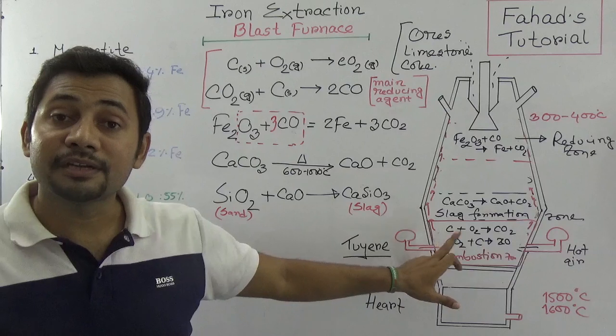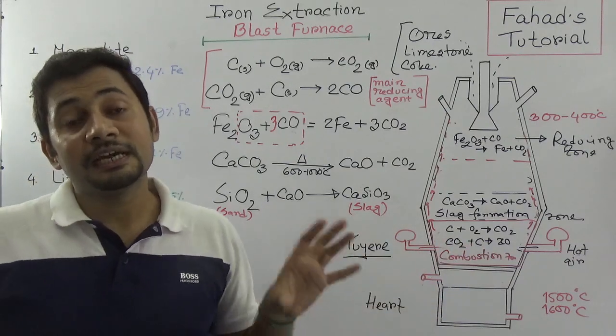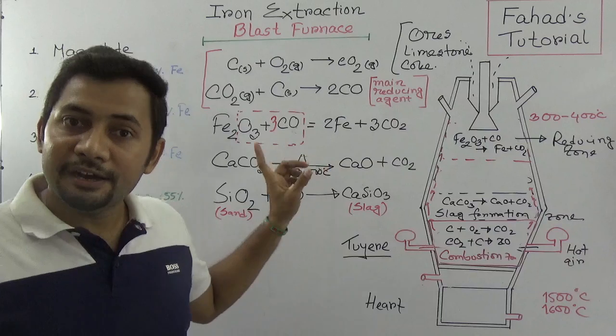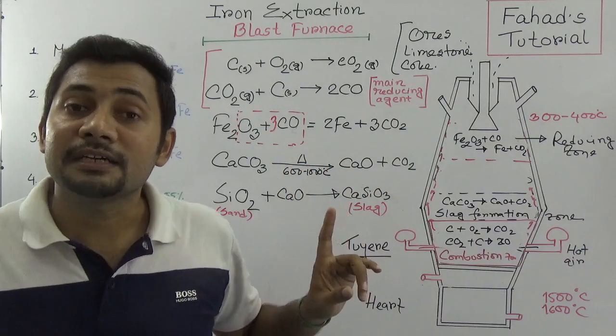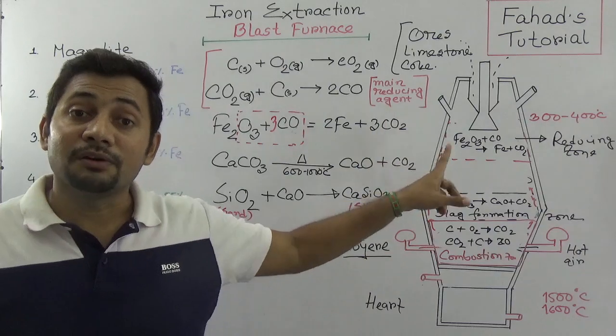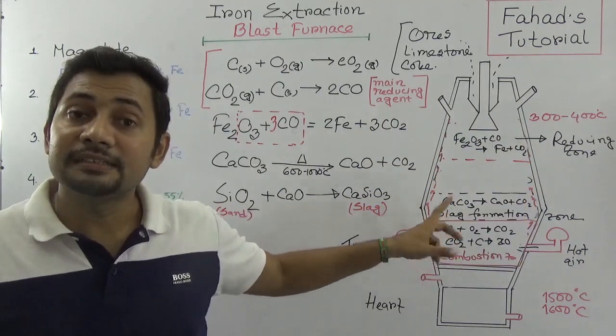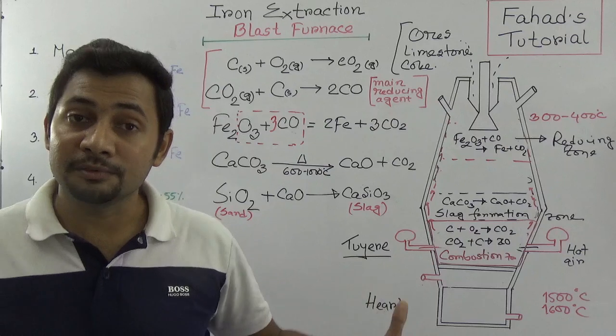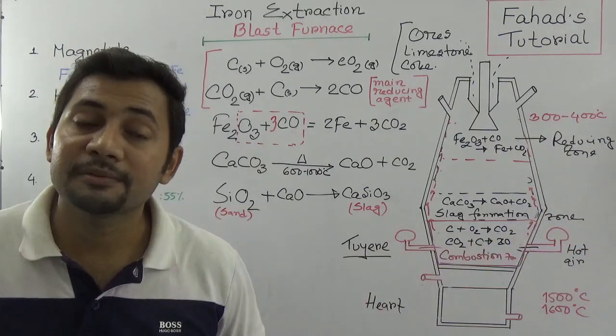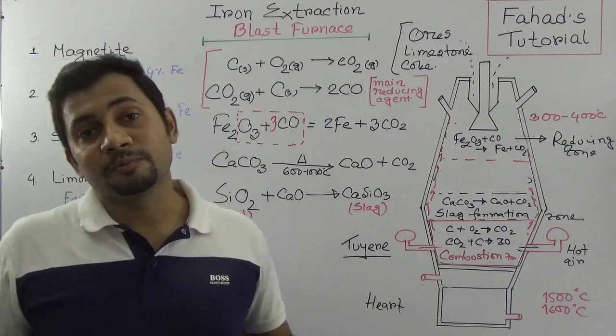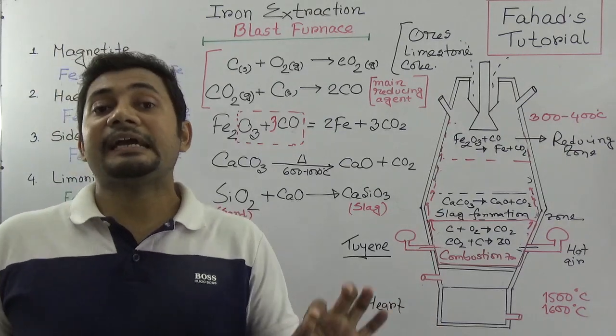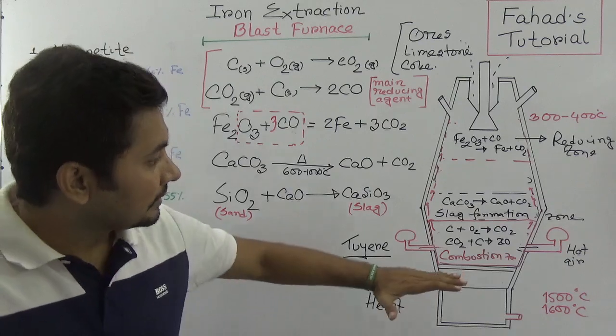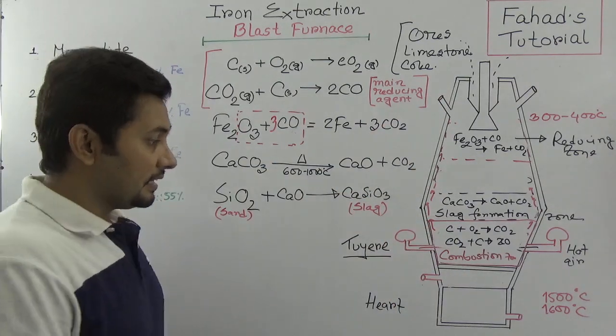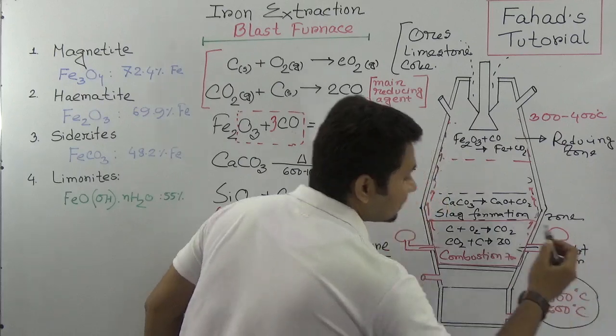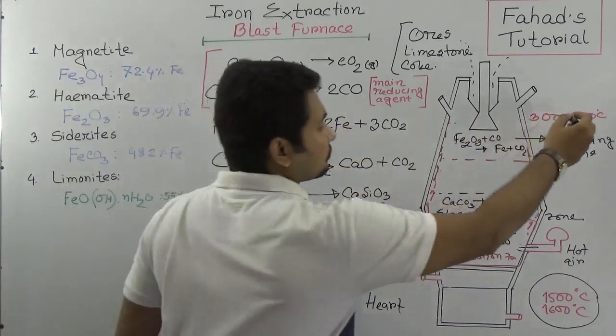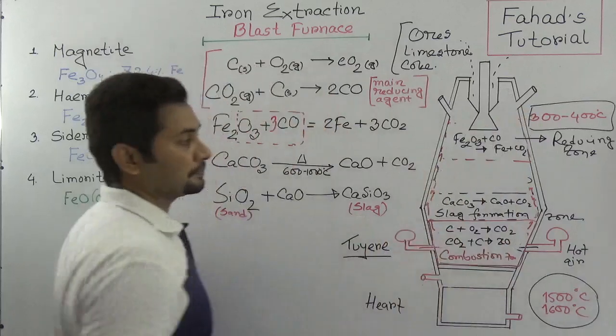So firstly, that carbon dioxide and carbon monoxide is producing, and that is called the combustion zone. The iron oxide is being reduced by the carbon monoxide, and that is called reducing zone. In other side, that calcium carbonate is thermal decomposing to produce calcium oxide and carbon dioxide, and that calcium oxide will produce slag, and that is why this is called slag formation zone. So in this case, the temperature varies from 1500 degree to 1600 degrees Celsius to 300 to 400 degrees Celsius.